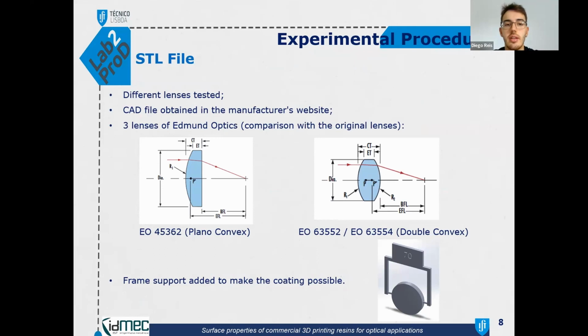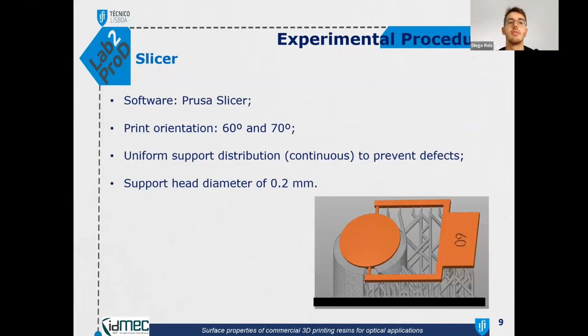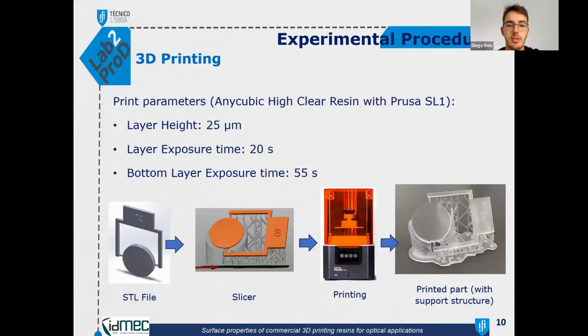To obtain the STL files, we intended to print 3 different lenses from Edmund Optics, 1 plano-convex and 2 double-convex with different thicknesses. We selected those lenses because we want to make a further comparison with the original ones. We obtained the CAD file from the manufacturer's website, and then added a frame support to make the dip coating possible. The slicing software was Prusa. We printed in an orientation of 60 and 70 degrees with a uniform support distribution in a continuous way in order to prevent some defects that could appear in the printing step, also with a support head diameter of 0.2 millimeters.